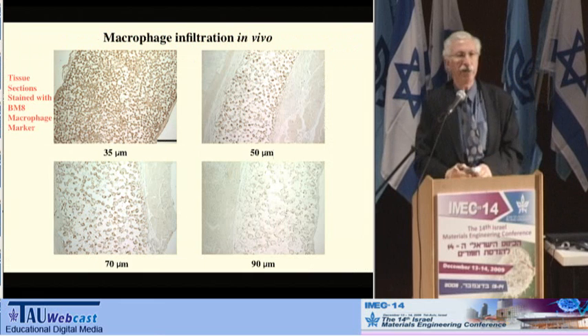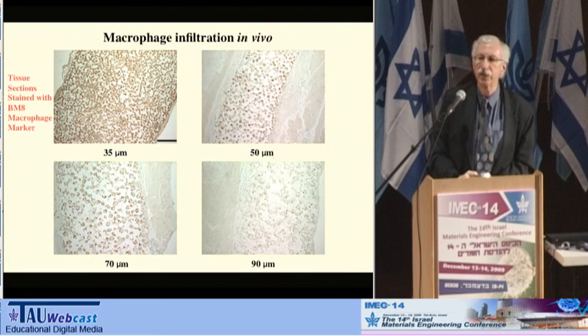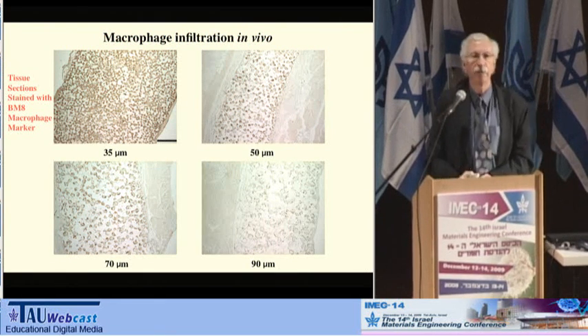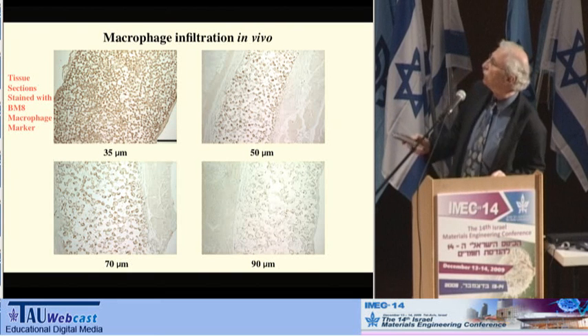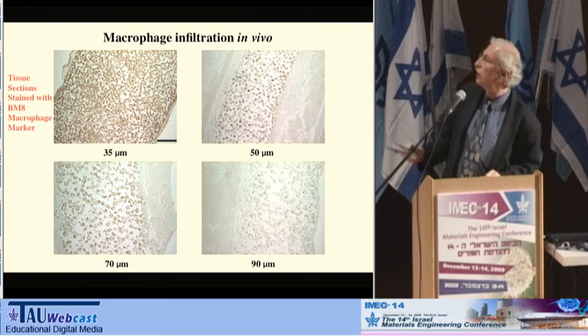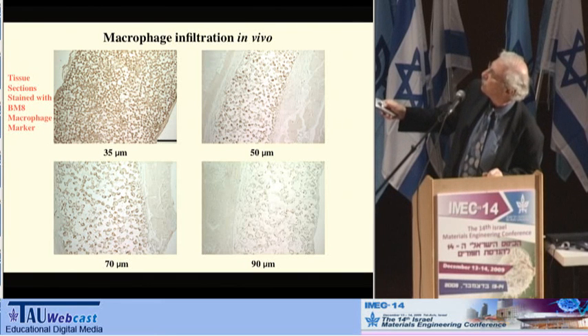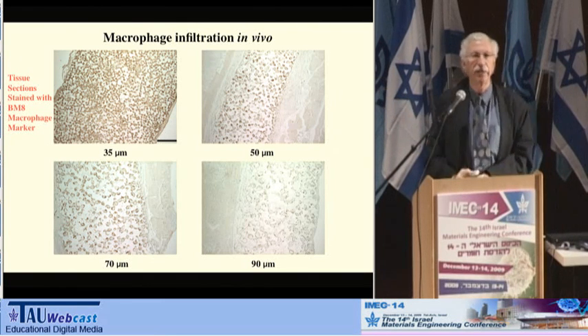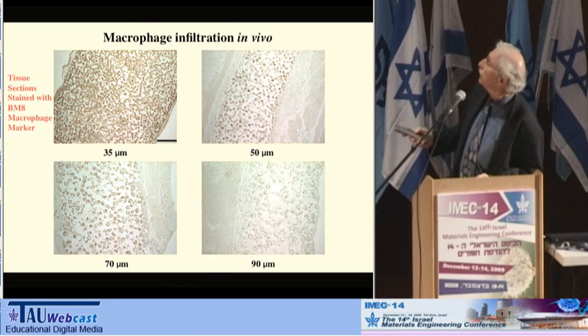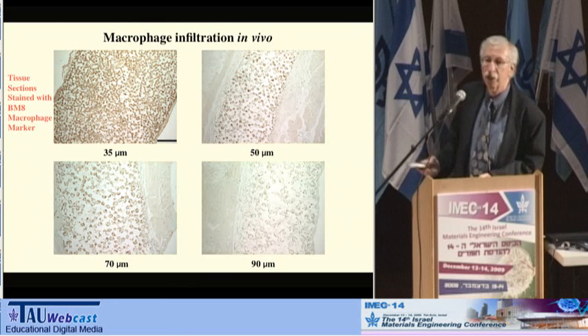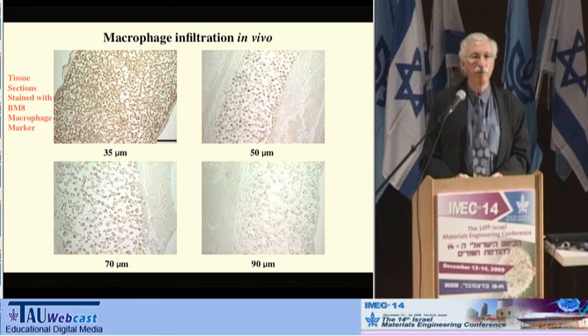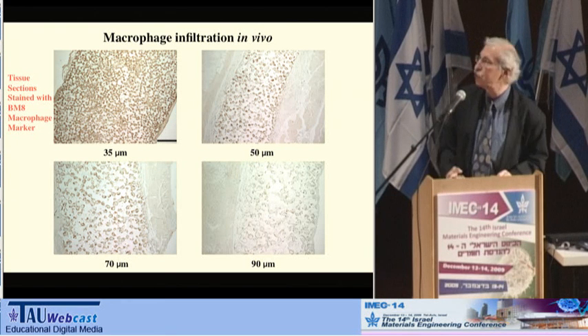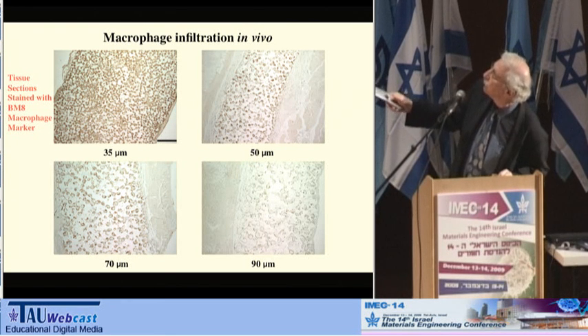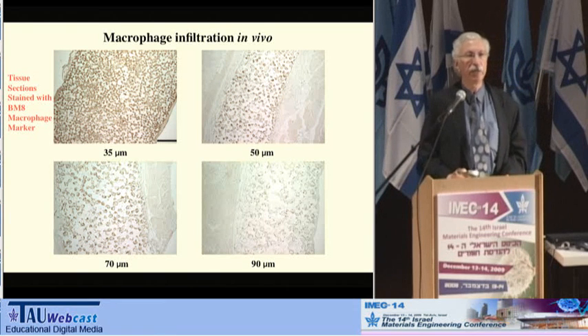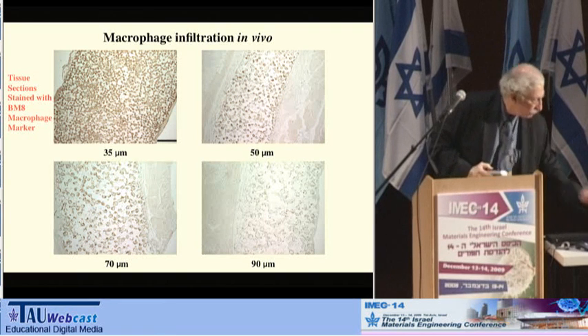And one of the interesting things in this healing response, this is a biological stain for these cells called the macrophages. It's specific to the macrophage cell, and the more brown, the more macrophages. In the 35 micron material, this is richly populated with these macrophage cells. Remember, all these materials are close-packed spheres, so they all have the same void volume, roughly 70%, and yet just the 35 micron is densely packed with these macrophage cells.